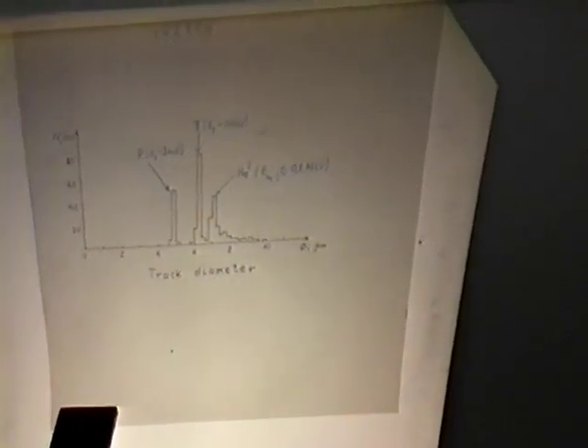Thus, we can see that these 3 types of DD reaction products can be detected and identified by the CR39 technique. We also need to note that this is the case of a very thin layer of interaction for DD reaction. If we have a thick sample, the track diameters may intersect with each other, and it's very difficult to estimate the yield of DD reaction from thick samples.